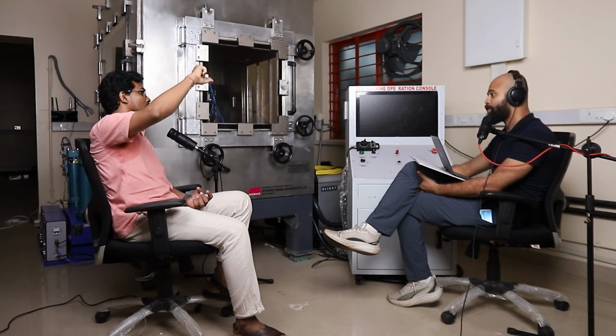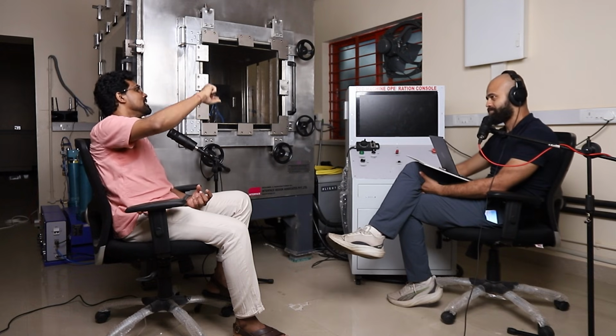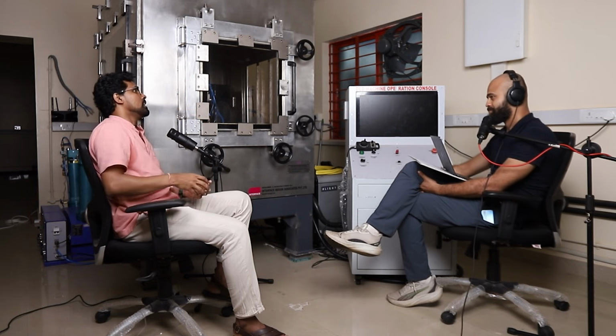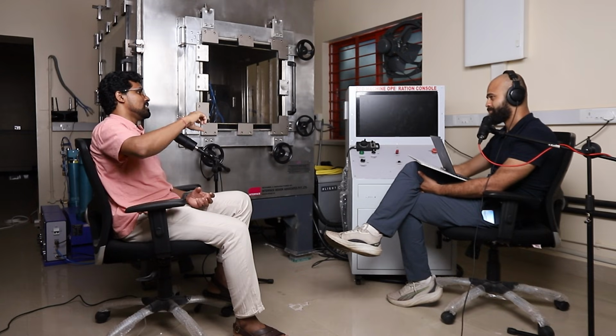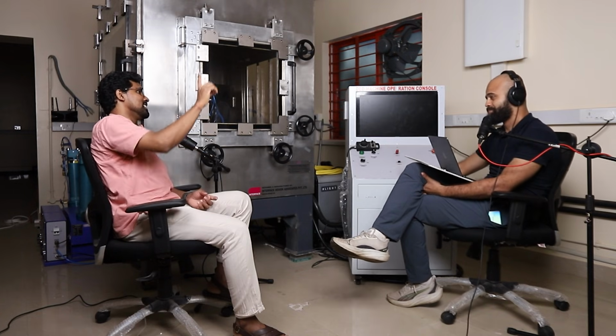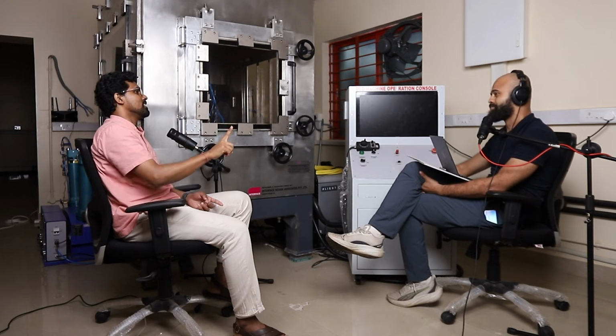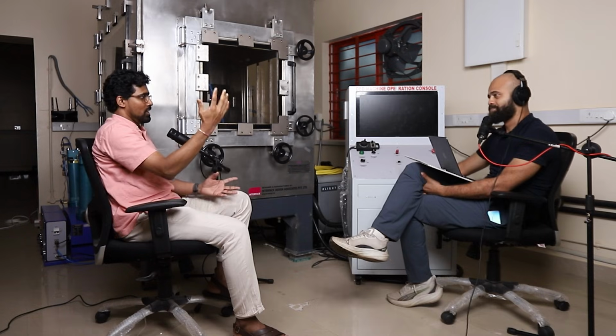Scientists were like, okay, how can we make it one single grain? To make a columnar grain, you cannot do it using a traditional casting process. You use something called a Bridgman type of solidification process where you have a temperature gradient. By temperature gradient, I mean you need a liquid to be cooling. If you want a directional property, I was talking about columnar, right, that is in one direction, so properties would be directional. If you can control the solidification process such that the liquid solidifies in one direction, in that radial direction, then you can get the columnar growth. So that was the idea, and that led to the development of columnar.